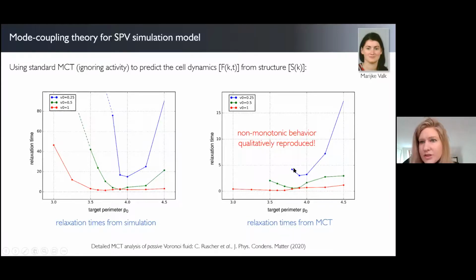And that's remarkable for several reasons. First of all, mode coupling theory has of course not been developed for cells originally. It was developed for ordinary simple glass forming materials. And yet it's able to capture this fairly non-trivial feature in the dynamics from only subtle structural changes in these cell layers. And secondly, we did a pretty crude job here by taking only the standard mode coupling theory that doesn't yet know that these cells are active. So we just assumed ordinary dead Brownian dynamics here, while in reality in the model, the cells are active as well. So even with that crude approximation to ignore activity in the theory, we captured this qualitative feature quite nicely.